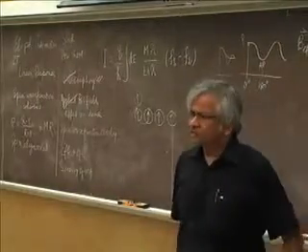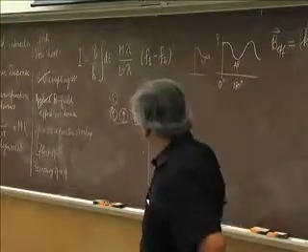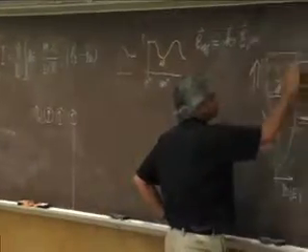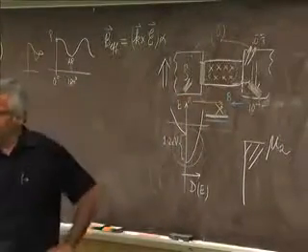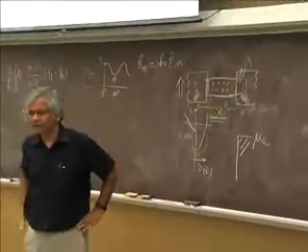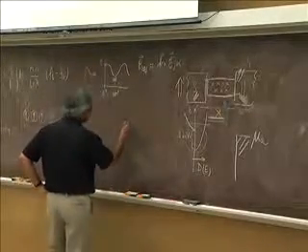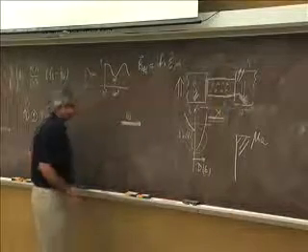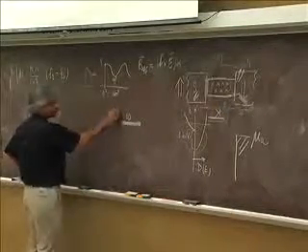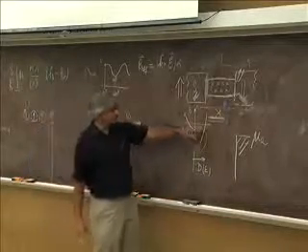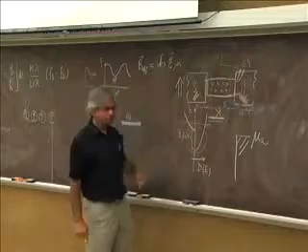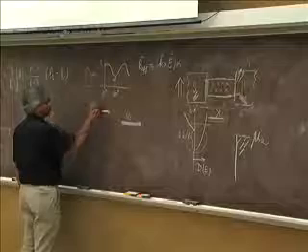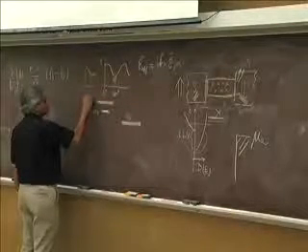Okay, and so similar issue about this, I think someone asked me about what does it take to make a good spin contact. And this is where I guess there's been a lot of work. I'm not sure if there's a consensus on the understanding of things, but my view of it is something like that when you look inside the channel, let's say you've got 10 lanes, and then you have this contact. And of course, what makes the two spins different is that you have different number of lanes in the contact. So let us say you got 100 lanes here for the minority spin and maybe 10,000 lanes for the majority spin.